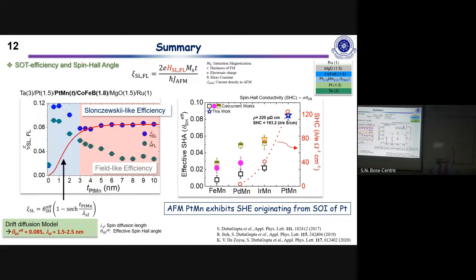And also, we compare our experimental data with the first-principles calculation, which is shown as the red circles, and the spin Hall conductivity, which is calculated from our experiment, and the theory roughly matches. So this indicates that in this system, the spin Hall effect is mainly originating from the spin-orbit coupling of platinum. So platinum is the major contributor to the spin Hall effect in this antiferromagnet.